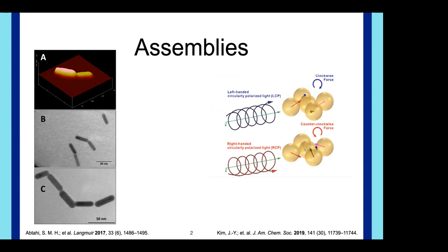In this case, we're starting off with monomer units of gold nanomaterials, whether it be a gold salt or a gold nanoparticle, or, on the left over here, a gold nanorod. In this case, they have individual rods. They're going to manipulate these in such a way that they assemble into specific shapes. Here, they introduced a sulfate ion, which changes the electrostatics of these gold nanorods so that they bind end-to-end rather than on the longer axis.